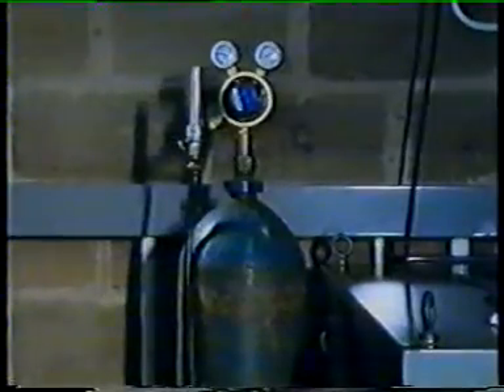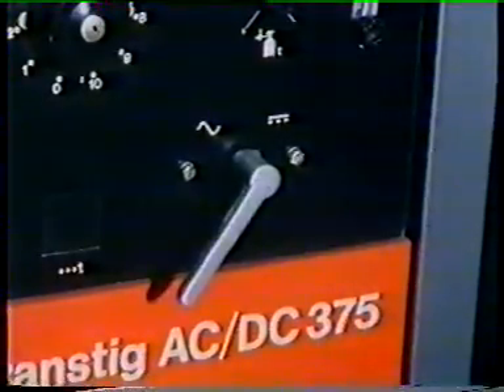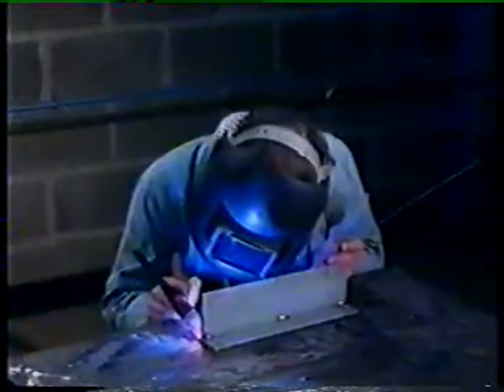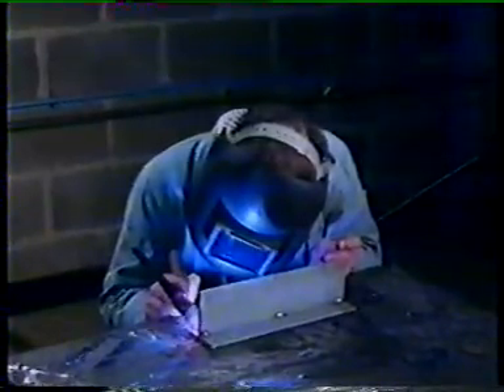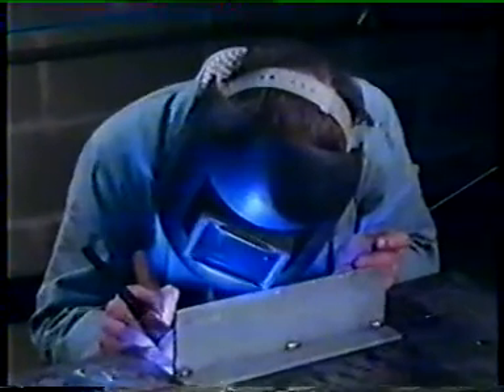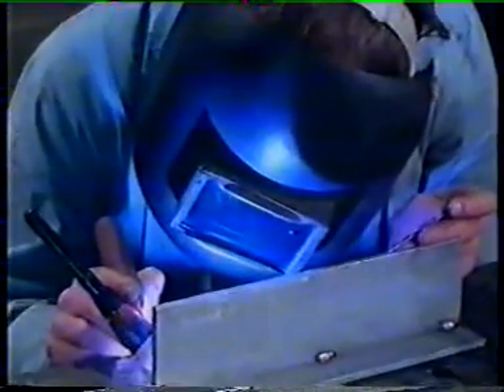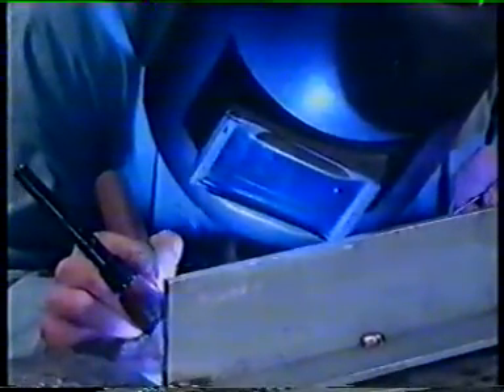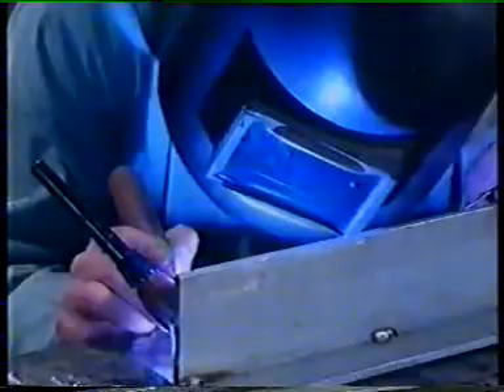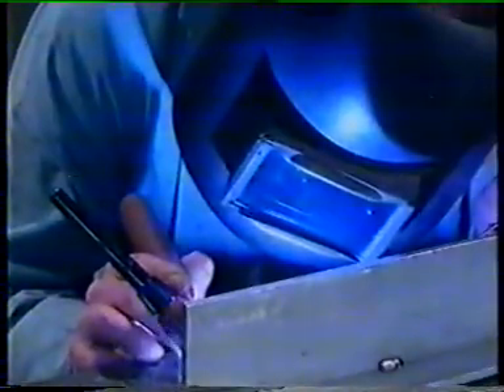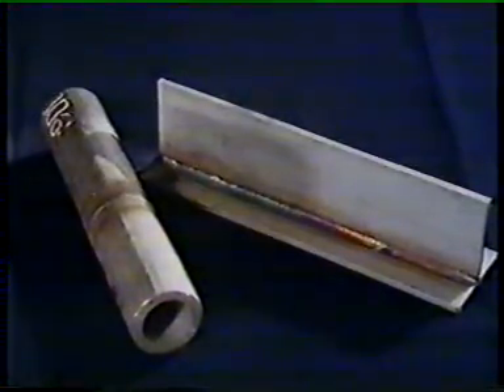With TIG, pure argon is usually employed as a shielding gas, and this is suitable for all metals. As with MIG, the nozzle is designed to match the flow characteristics of the argon. Direct current with the electrode connected to the negative pole of the power supply unit is used for all metals except aluminium. The degree of control which this gives the welder makes the TIG process particularly suitable for the welding of sheet metal. Welds can be deposited in almost every position, but it calls for a high degree of skill and experience. TIG welding is often used in this way for the fabrication of pipework for high-pressure steam lines and for chemical plant.